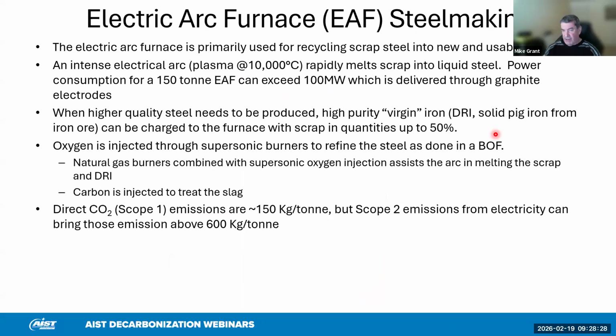The electric arc furnace steelmaking is becoming more and more common, especially because it is much more friendly from a CO2 footprint point of view. In the US, 72% of the steel made is from the electric arc furnace. It's designed primarily as a scrap recycler. As Joe mentioned, steel is virtually 100% recyclable, and recycled scrap can be melted and made into new and usable steel. It's done using an electric arc that produces a plasma of roughly 10,000 degrees C, rapidly melting the scrap into liquid steel. It uses more than 100 megawatts for the typical 150-ton batch of steel produced. This power is delivered through graphite electrodes into the bath.